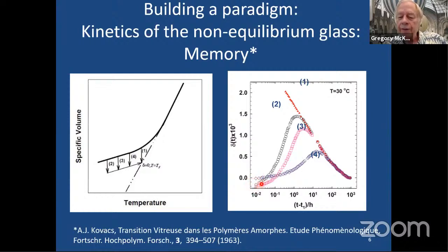But look what happens. We get this crossover of equilibrium. This is the equilibrium volume, and yet the sample doesn't stay in equilibrium. It shows a memory, and it remembers how I got to that fictive temperature. Okay, so that's the memory effect. And this shows that, in fact, the kinetics lead to a glassy behavior, which is path dependent in addition to being temperature dependent. So it depends on not only departure from equilibrium and temperature, but it also depends on how I got there.